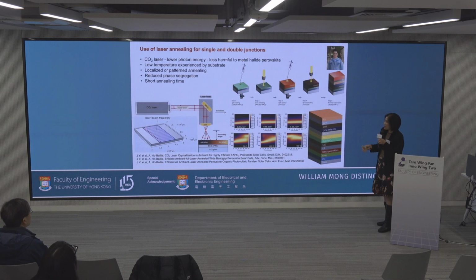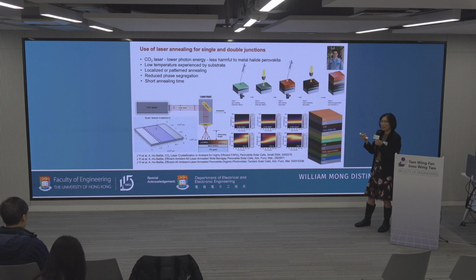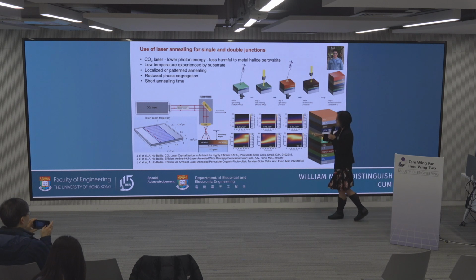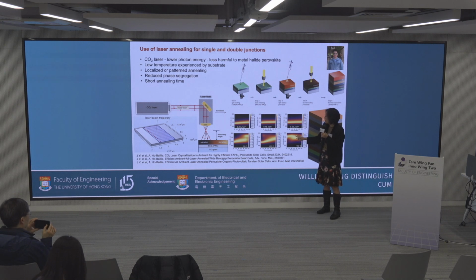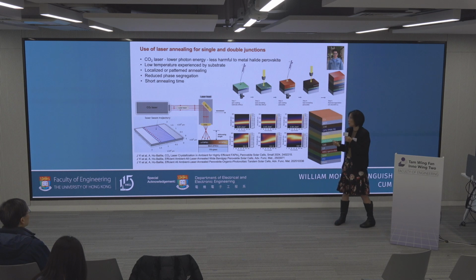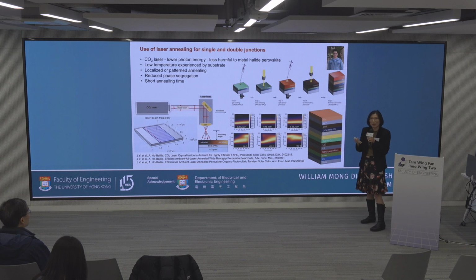Okay, so that's something that if you're interested in looking at using different annealing process rather than hot plate processing for annealing perovskites, it's a lot shorter. We're using a CO2 laser because it's a lot gentler on the perovskite bonds, and it enables localized patterning. And one thing we found is that the substrate is a lot cooler if you use laser. And also we found that you don't see the phase segregation as you will see with hot plate anneal. We still don't quite understand why the phase segregation is suppressed in laser anneal process, but it could be because of the strain in the film that is different when it's laser annealed.